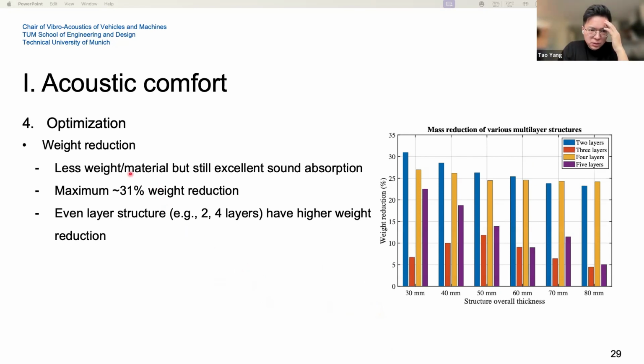As I mentioned, because we could reach comparable or still great sound absorption, I use a multi-layer structure, so we can somehow lower the weight of the material, because it's not really possible to decrease the thickness if we are only using very simple porous or fiber material. But with a multi-layer structure, we still reach good sound absorption with a very good weight reduction. For example, this one, the maximum weight reduction is around